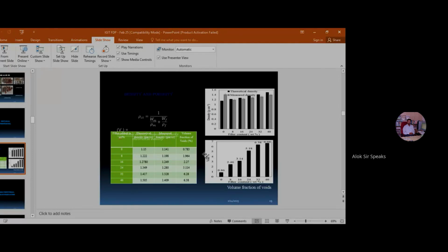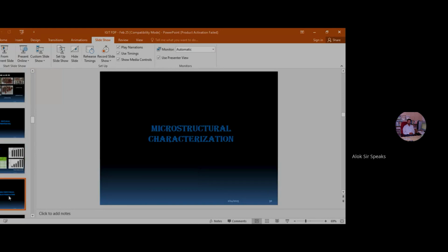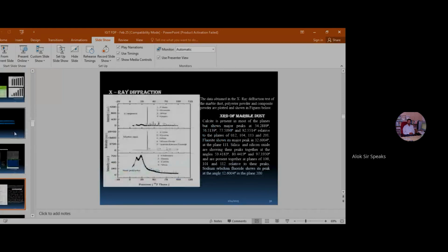So these are the data. I'm not reading out the data, but you can see that as the filler content, the marble dust percentage, is increased, the voids also increase. That is the reason, because sometimes our stirring is not proper. Sometimes there is improper wetting. There are irregular, sharp edged corners of the particles which are not getting fully wetted by the liquid polymer, and so on. There are various reasons which need further investigation.